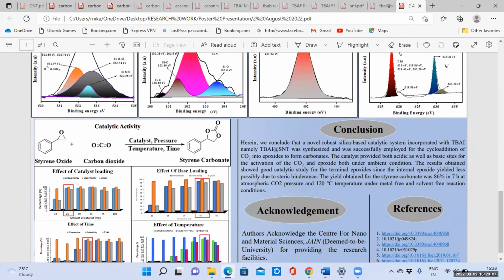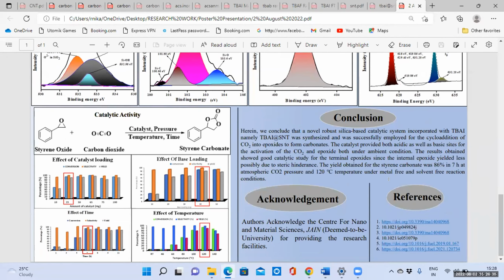Herein, I would like to conclude my poster presentation. That is, we synthesized the novel robust silica-based catalyst which was incorporated with TBAI, namely TBAI@SNT catalyst, and was used for cycloaddition of CO2 into epoxide to form carbonates under ambient condition, which yielded 86% of yield for styrene carbonate in 7 hours at atmospheric pressure and 120 degree temperature under metal-free and solvent-free condition.